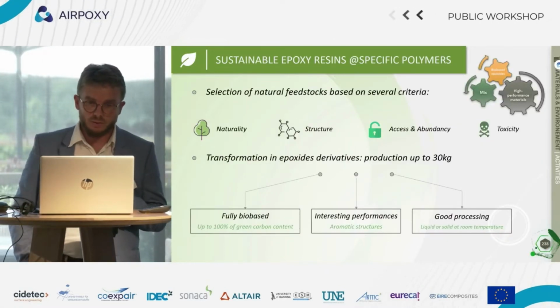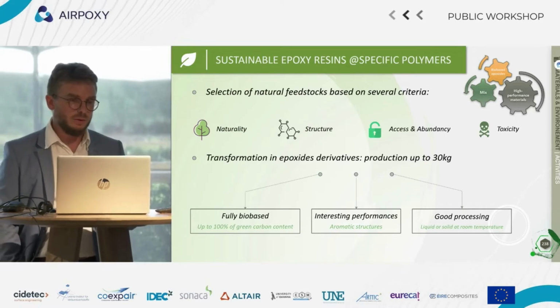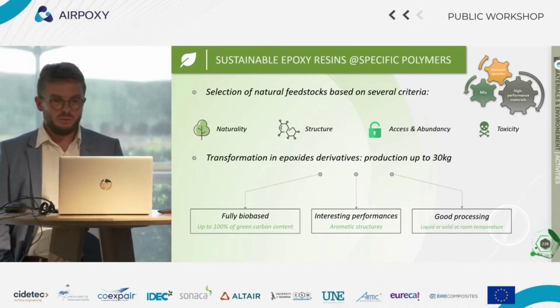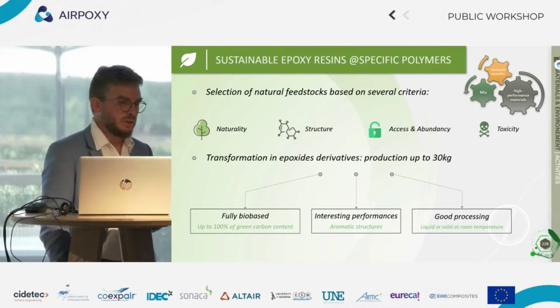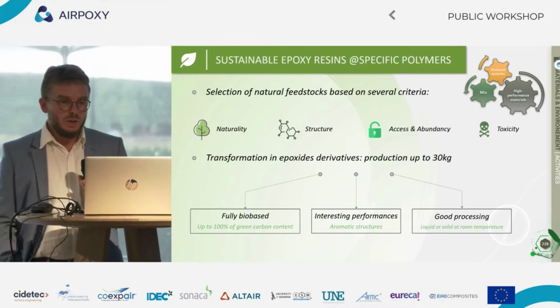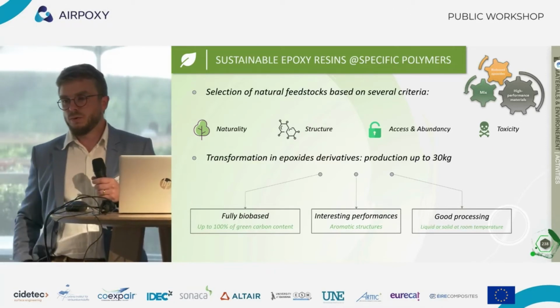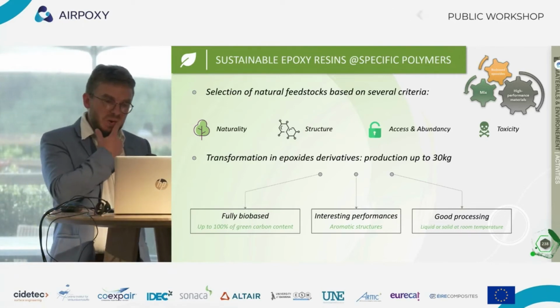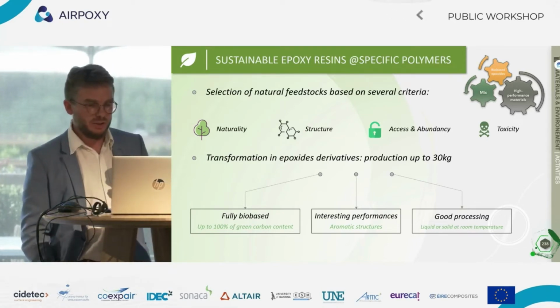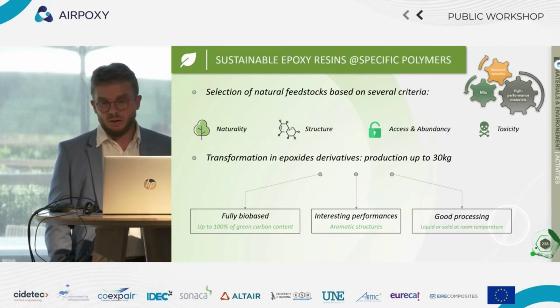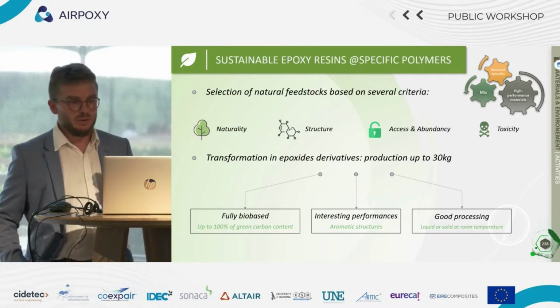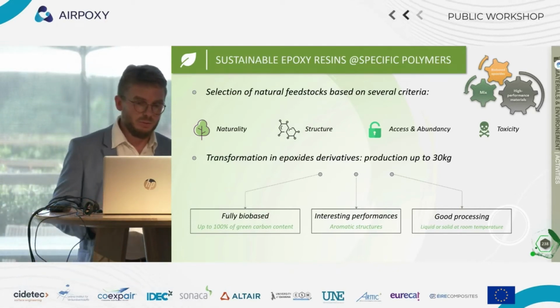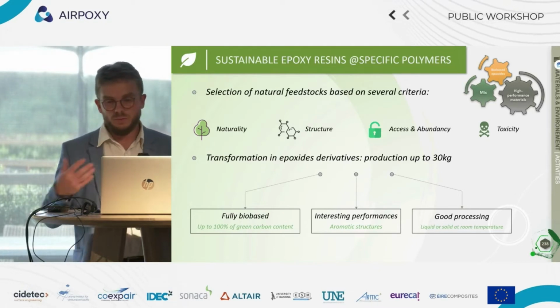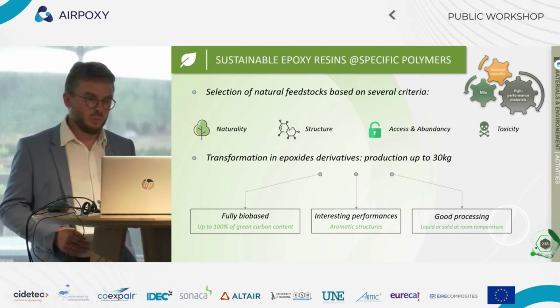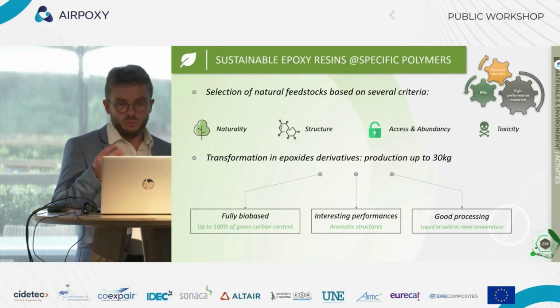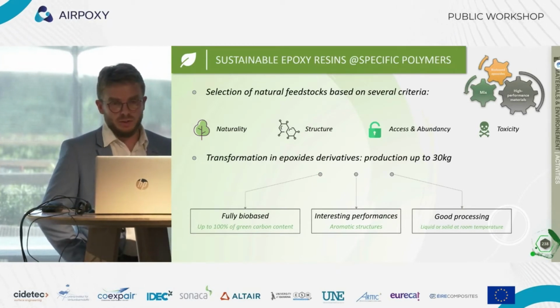So if I go back to the selection of the precursors, the main aspects we take into consideration when we select precursors from natural resources are first their naturality, of course, and their chemical structure. What we want is to have, I would say, a range of properties from low Tg to, I hope, high Tg in the future. And so we are selecting aromatic, aliphatic, and cycloaliphatic compounds in order to have this variability. And also in terms of physical properties, you need some molecules that are viscous, you need some molecules that are very liquid, and play with them in order to make a suitable formulation. So this we can tune at the early selection of the chemical structure.